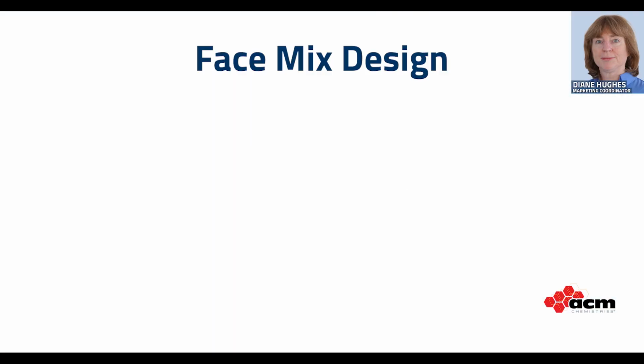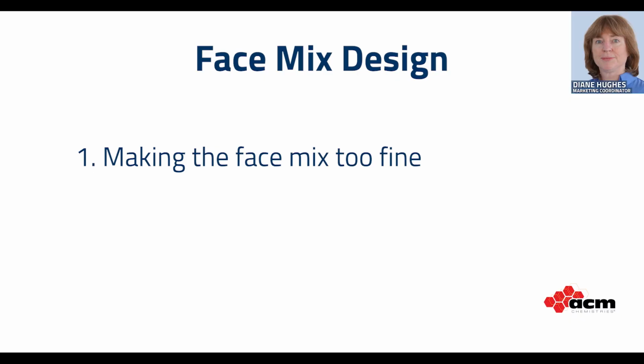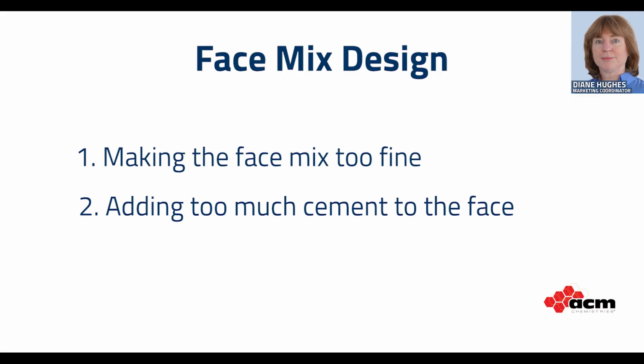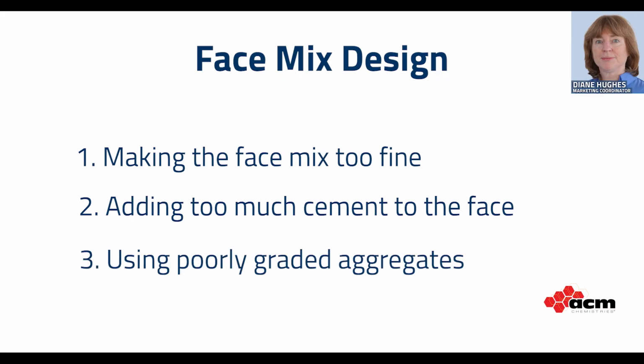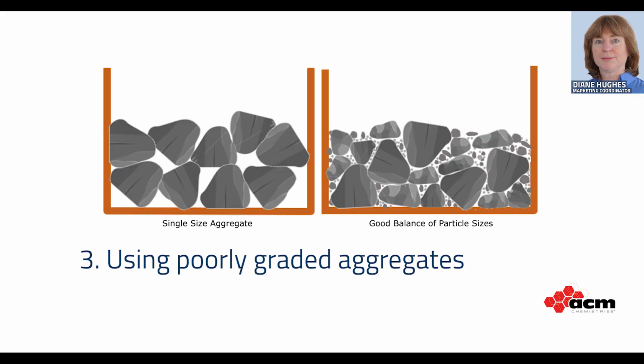Most face mix pavers work just as intended. Occasionally, we get called in to help with issues that are caused by these three mix design mistakes. Number one, using very fine aggregate in the face layer. This can happen when production is told that only the smoothest, most mirror-like surface is acceptable to customers, so production tries working with a mix design that is overloaded with superfine aggregates. Number two, adding too much cement to the face, again chasing that super smooth finish. And number three, using poorly graded aggregates, especially aggregates with only one size that do not pack well.